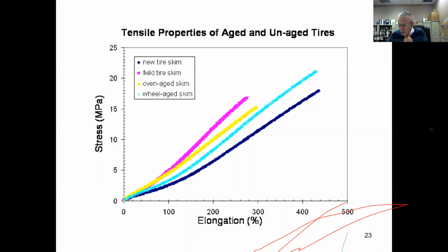And I don't show it, but sometimes I could have included, but I didn't. We have the crack growth data, okay, and we compare the crack growth data, and of course these have much higher crack growth rates than the unaged, and these two are not significantly different. So even though they have different crosslink types, they have the same tensile properties and the same crack growth properties. Okay.